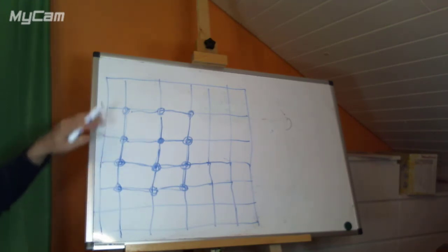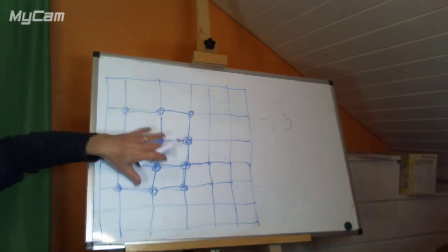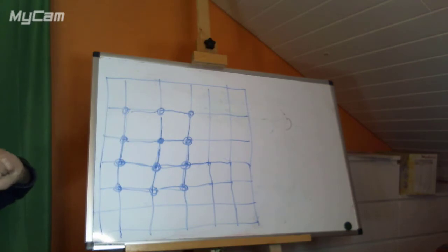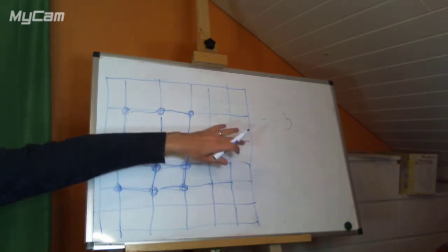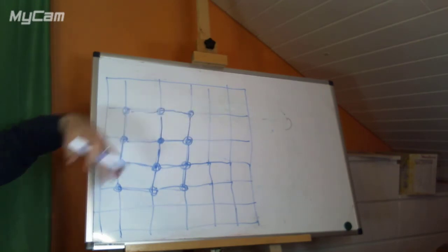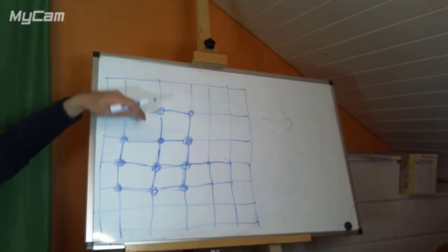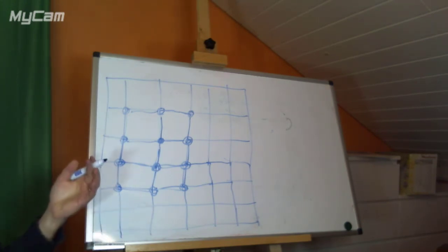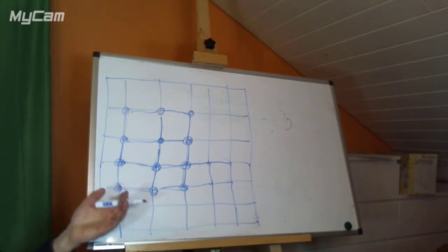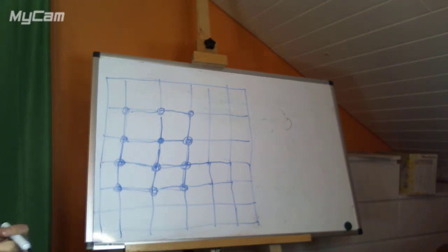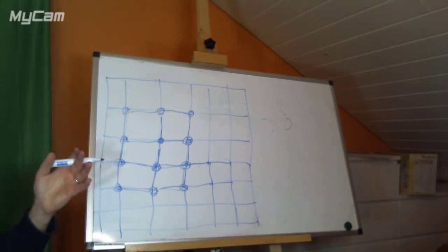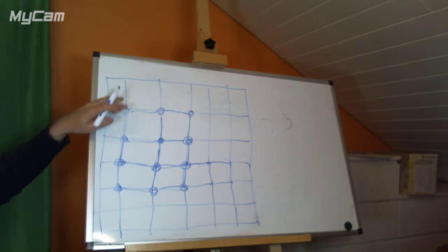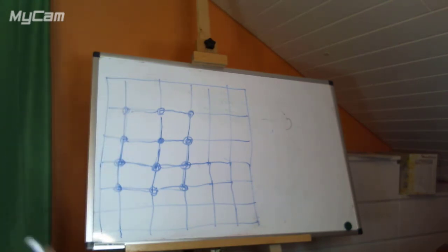If we have a lot of energy in our system, it will start a lot of islands all over. If we just add enough energy so that it can start one island, then it will grow completely. And then it will stop again because it doesn't have enough energy to make a new one. So if we can control the energy in the system, which is temperature in many cases, or voltage if we're doing electrodeposition, if we can control the energy very carefully, we can stop it at a reasonably finished level. However, there is a problem.